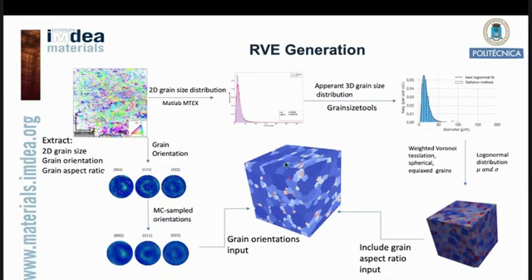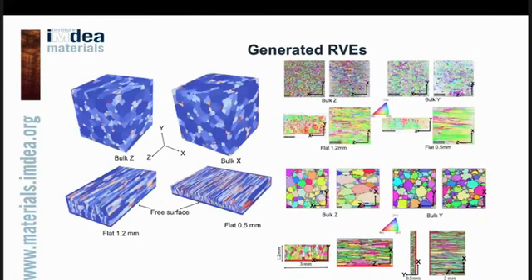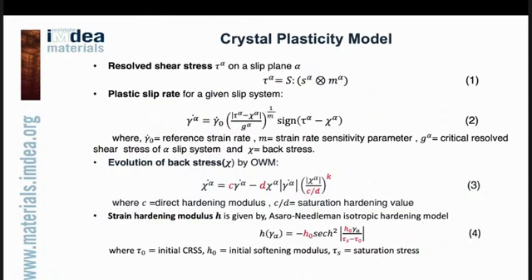So in our RVE now, it's very likely to the actual microstructure, which we will use further. These are some of our earlier work, where we built some RVEs for the additive manufactured sample, and you see a lot of elongated grains, which is very similar to our actual EBSD test. Then I will quickly go to the crystal plasticity model.